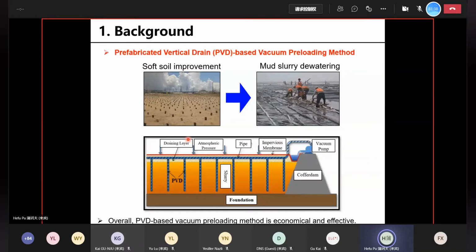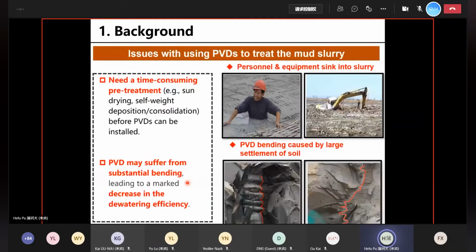And there are many methods out there to treat the high water content mud slurry. One commonly used is the prefabricated vertical drain, the PVD-based vacuum preload method. This method has been used for many years in the field of conventional geotechnical engineering for soft ground improvement. And more recently, people have started to use it for mud slurry dewatering. So the idea is simple. We simply insert the PVDs, the vertical drains, into the ground, and then connect the PVDs with vacuum pumps, and then we apply a vacuum pressure, and then the vacuum pressure can suck out the water and reduce the water content. And overall, the PVD-based vacuum preloading method is economic and effective, but still there are many issues that need to be solved when using PVDs.